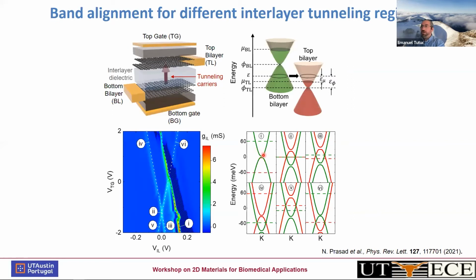So what I'm showing here with green and red are the bands of the two layers, and they overlap, but their Fermi level could be different. Okay, so when this condition is realized, that's when tunneling is favored. And when we're away from this condition, tunneling is suppressed, hence this gate tunable negative differential resistance. So this is one interesting effect that is not easy to implement in III-V or silicon-germanium heterostructures, even more difficult to make gate tunable. And in 2D semiconductors, thanks to the 2D nature of the confinement, this is easier to implement and also appears to be rather immune to temperature.